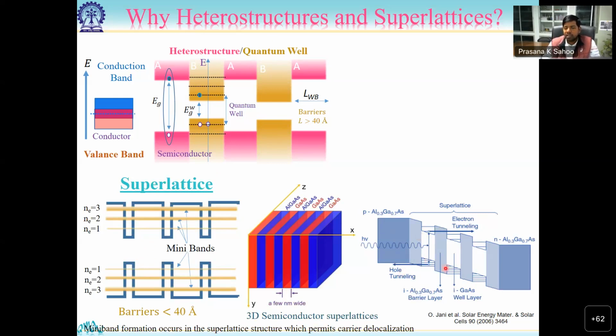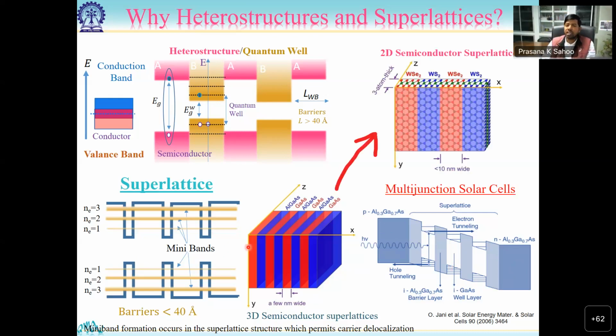So these are good for, like, realizing very high-efficiency solar cells. Here, electrons and holes can effectively tunnel from one layer to another layer, so that efficient charge extraction can happen. Because in many solar cells, the charge can be excited, but they can recombine again very quickly. So to avoid that recombination, we can make this superlattice structure. But it's easier to grow layer by layer in semiconductors. For 2D materials, it is really challenging to grow layer by layer like a superlattice. It's still a challenging job.